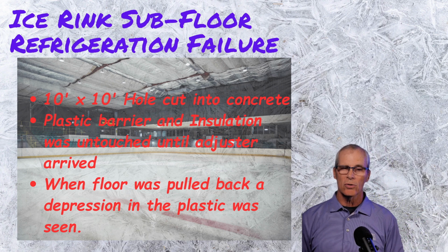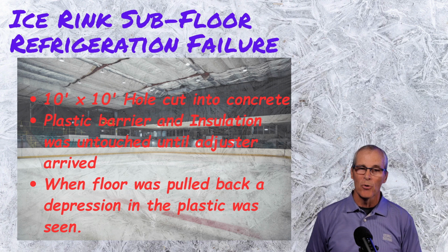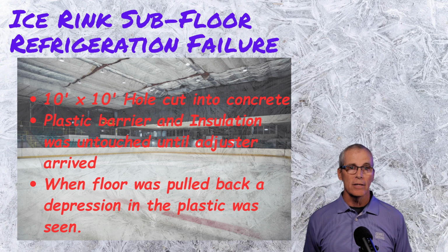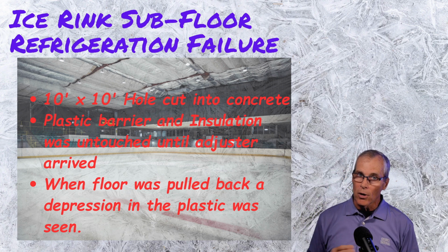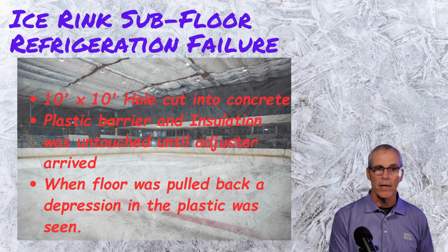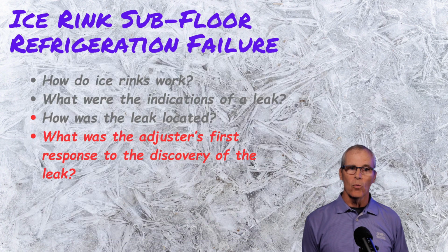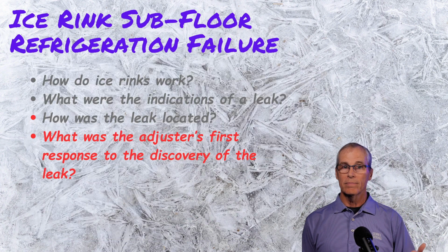The adjuster's looking at it, and before I can even nudge him in the direction of a brittle fracture, he recognized right away that it was not a fatigue crack, that it was definitely a brittle fracture. It happened at once. It didn't happen over time. So he was certain that this was a failure, but he wasn't quite sure that it was the one that caused the floor to fail.